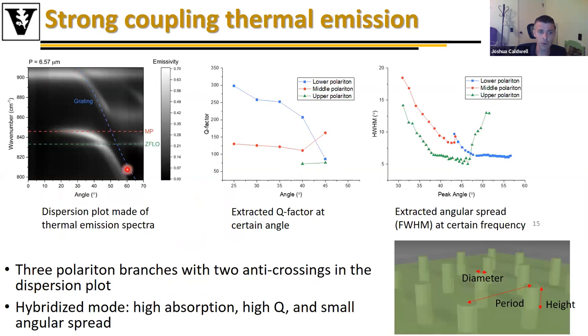And you can see I have my grating mode that would ordinarily be dispersive along this blue line. My monopole resonance, which would ordinarily be nominally non-dispersive and flat here. And then the zone folded LO phonon, which would also be non-dispersive, right? By incorporating this grating mode, I can now get strong coupling between the monopole and that grating mode. And much like Grafea's work, induce some spatial coherence here. But I can also use this to control the lifetime or the quality factor of these resonant modes, right? While also using this zone folding and its proximity to these polaritonic resonances to tune this around as well.